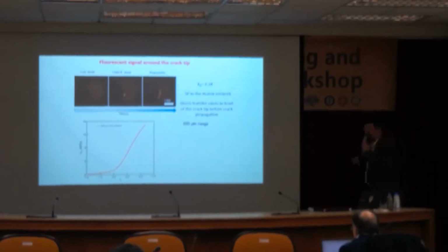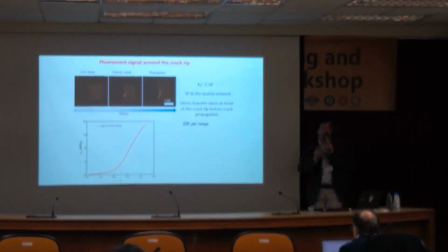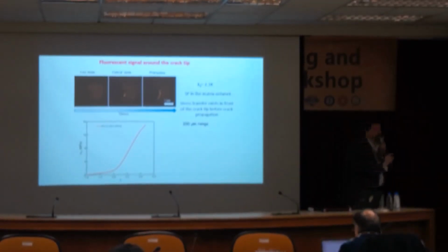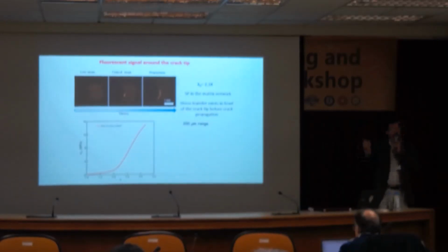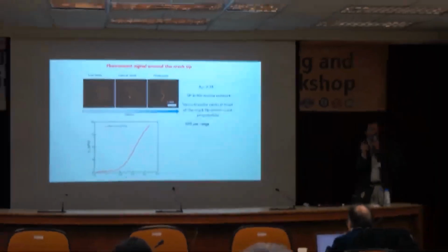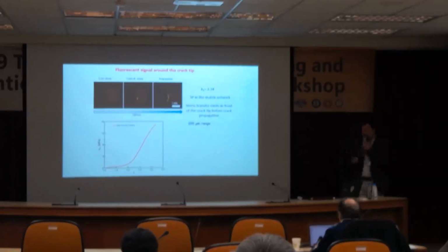So what it tells us is in most of these tough materials, breakage occurs in two steps. You first break some stiff phase, and then you break the soft phase. And the transition between the two and what controls it is very much a collective effect, where we just start now to understand a little bit better how it works.